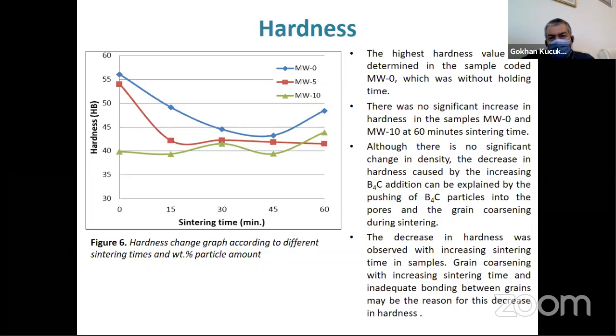The decrease in hardness was observed with increasing sintering time in samples. Grain coarsening with increasing sintering time and inadequate bonding between grains may be the reason for this decrease in hardness.